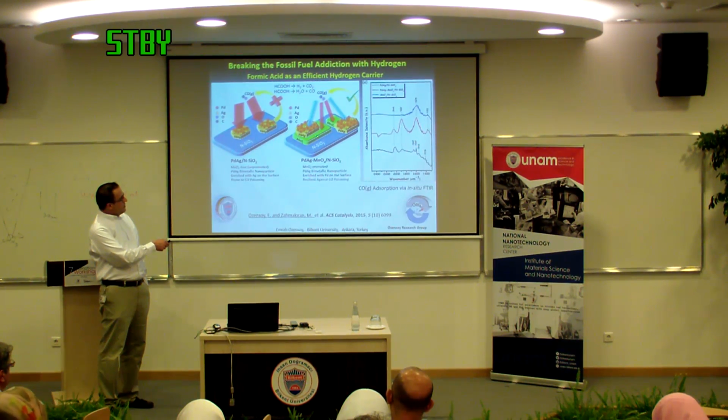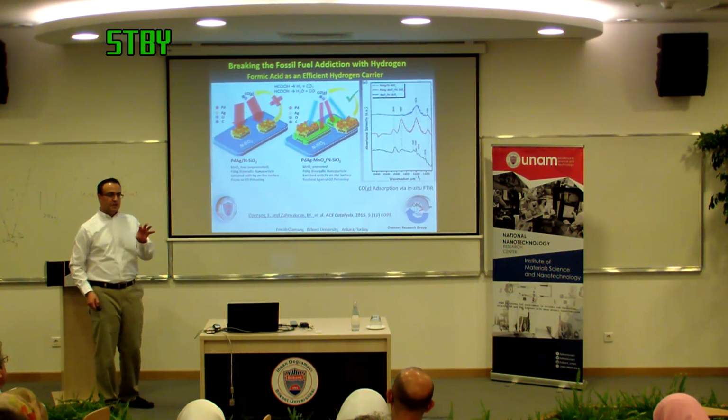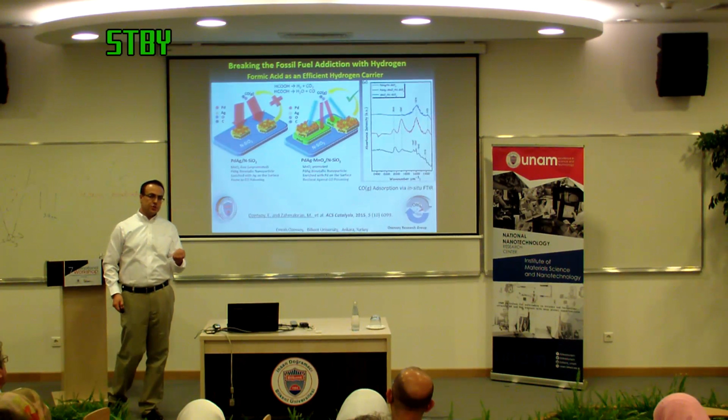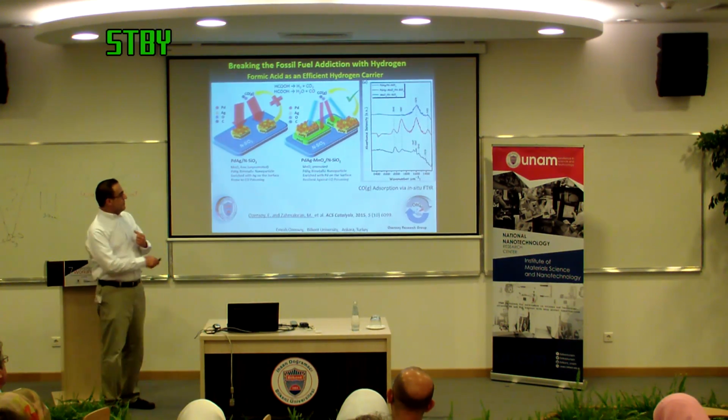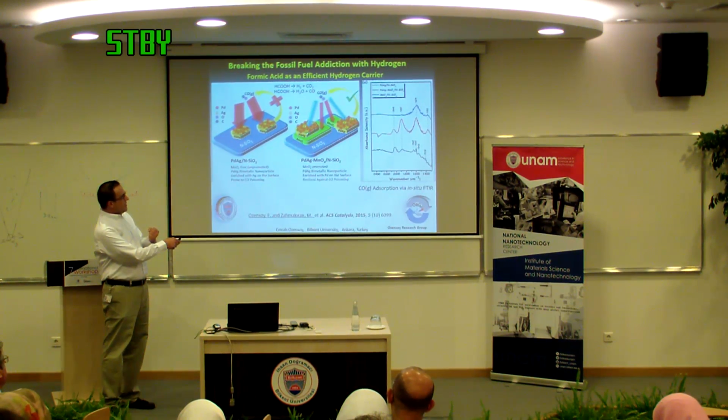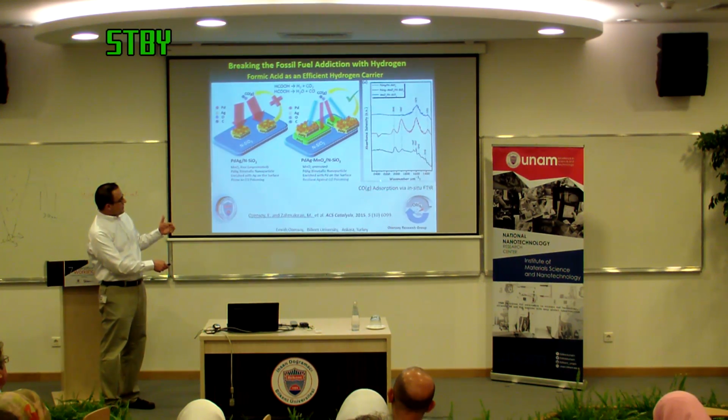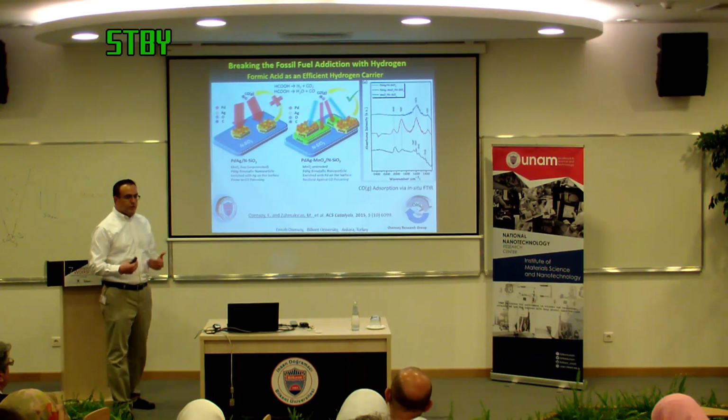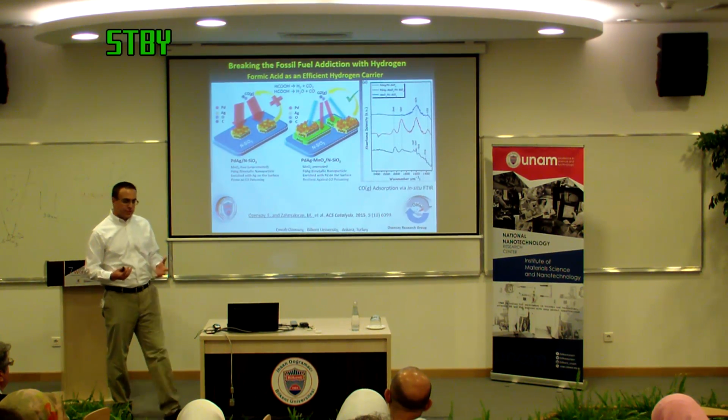So then what does CO do? It goes to the sacrificial site, which we add as manganese oxide. It forms carbonates. That means this promoter is a sacrificial CO suction unit. It sucks the poison, keeps the active site basically clean of CO, and by using in situ infrared spectroscopy, we've verified that these manganese oxide and palladium-silver bimetallic nanoparticles work like a charm. They're not only active, but also tolerant to CO poison.